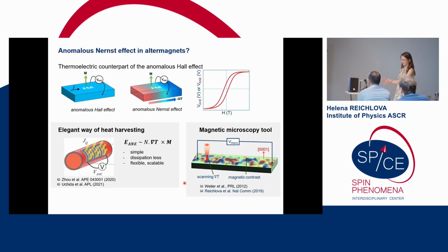Good. The last thing I wanted to mention is that I mentioned the anomalous Hall effect, but there is also the counterpart, the anomalous Nernst effect, right? This is just replacing the electrical current by a thermal gradient. We do expect almost the same signal. And I mention it because this anomalous Nernst effect is very interesting, not only as an elegant way of harvesting heat, but also as a magnetic microscopy tool, as Matthias was explaining, giving access to magnetic microscopy in systems which are otherwise invisible in conventional magnetic microscopy techniques.